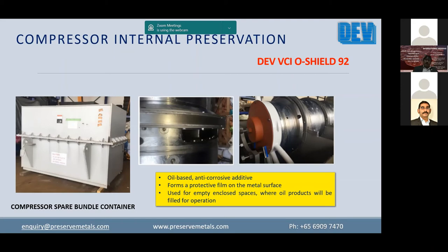So normally what we recommend is that once in the yards, the fabrication yards, the equipment or the systems are ready, if it's an oil-based system, for the empty system, we would recommend using this product so that you will never have a corrosion-related claim in these systems. And this protects not only the piping, it protects the tanks, the filters, the pumps, the entire equipment within this system.